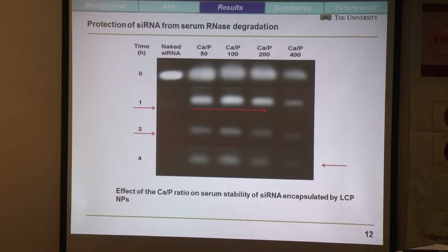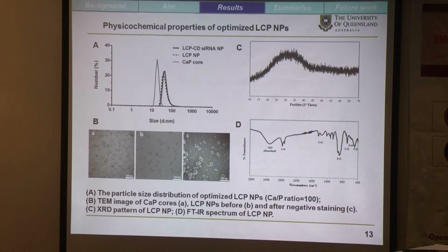Relatively, a large proportion of siRNA was protected by LCP nanoparticles prepared at the ratio of 50 to 200 in 2 hour incubation with serum, and the protection can be extended to 4 hours. And we also found that the protection provided by the LCP nanoparticles prepared at calcium to phosphate ratio of 100 seems to be the highest. So considering the loading capacity and the protection of siRNA by the LCP nanoparticles, we may suggest the calcium to phosphate ratio of 100 as the optimal ratio to prepare LCP nanoparticles, which will be used in the subsequent testing.